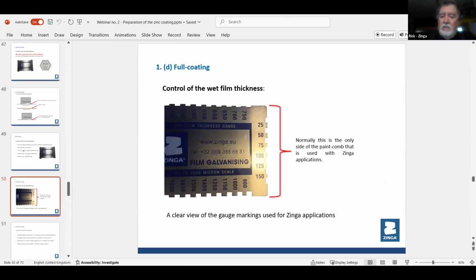On the smaller areas, this is the side that we use, because if you're going to be welding steelwork, after it's been coated, it's going to be lying around a shipyard or somewhere for a few weeks, you put on 60 microns, and then you can pick it up anytime. It's fully weldable at 60 microns. So in that case, you would apply here, say between 100 and 125, so it might just touch the one edge of the 125. So you know it's about 100, 115. It's going to dry at 60 microns.